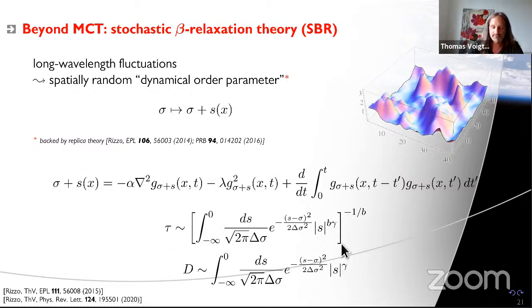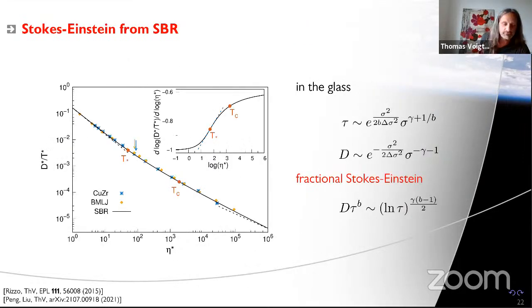And there's an interesting fact that I want to sneak into this talk: superficially, what you get here is something to the power of b times gamma. Those are both exponents that we know how to calculate from the beta scaling equation, to the power of -1/b. So if I could just multiply them together, I would have something to the power of minus gamma. And the mobility would be something to the power of plus gamma. And if I form the product, it would be approximately constant. And this is exactly what happens on the liquid side of the mode coupling transition. But if you have these integrals over Gaussian fluctuations, this argument is actually no longer valid. And it predicts something that when I first saw it, I thought was utter nonsense, to be honest. It predicts what has been called a fractional Stokes-Einstein relation. So there you go.